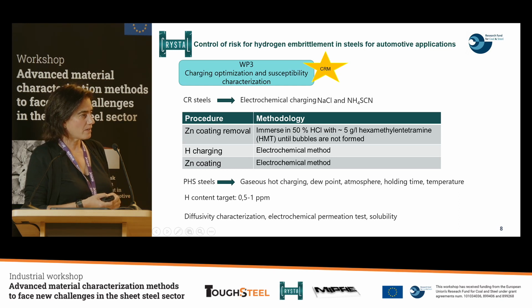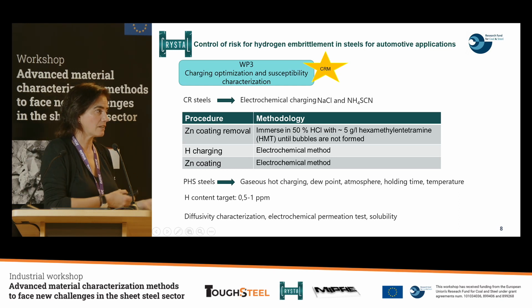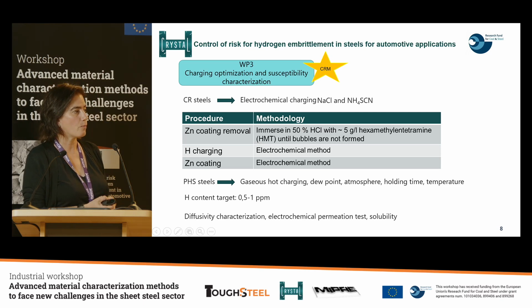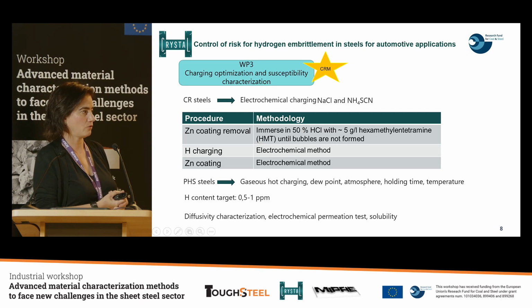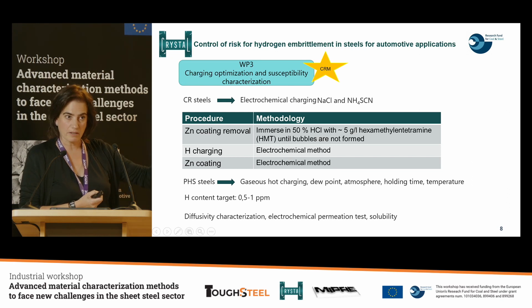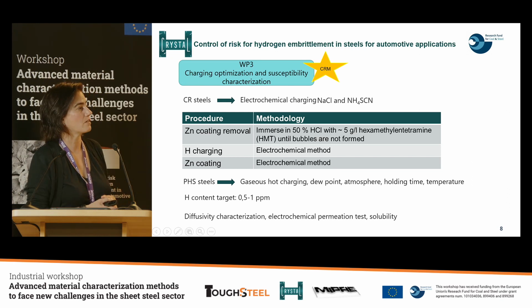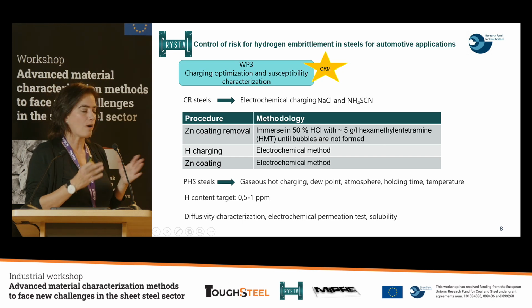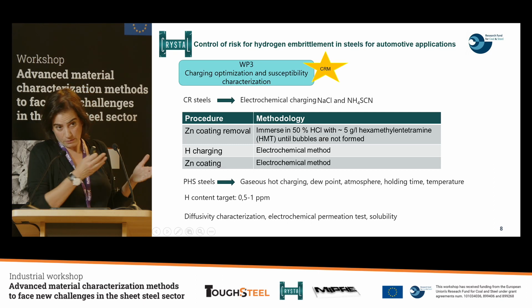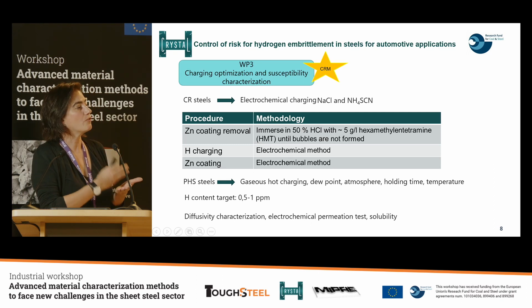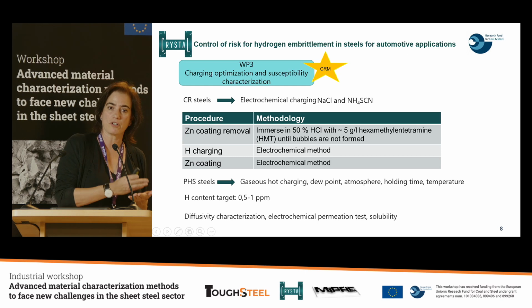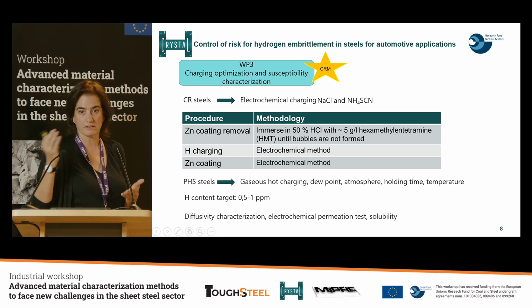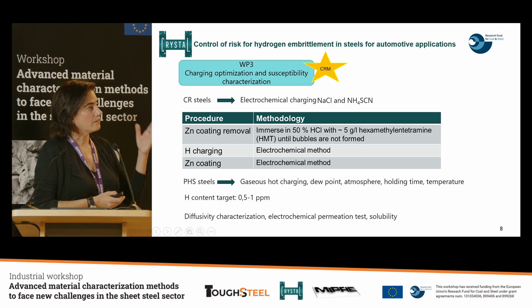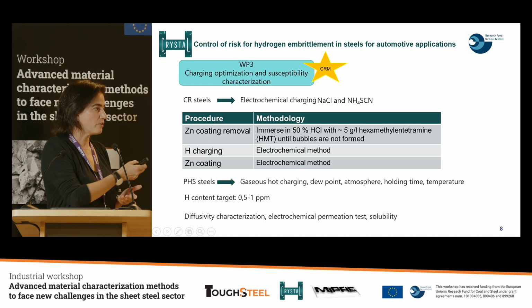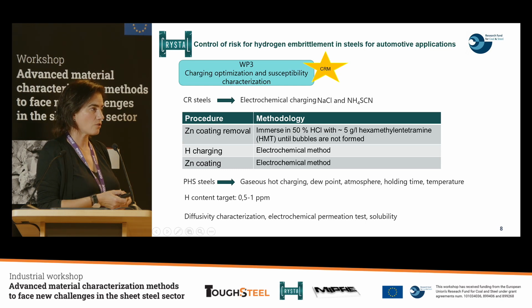And in the case of the PHS steels, we hot charge this type of steel, modifying the dew point, the atmosphere, the holding time, and the temperature. Later on, Mélodie Mandy will explain the optimization of these charging methodologies. Our hydrogen content target was between 0.5 and 1 ppm. We know that this value is far from reality, but we had to fix at least 2 hydrogen contents to perform the tests in work package 4. Okay. In this work package, we also characterize in terms of diffusivity, electrochemical permeation, and solubility.